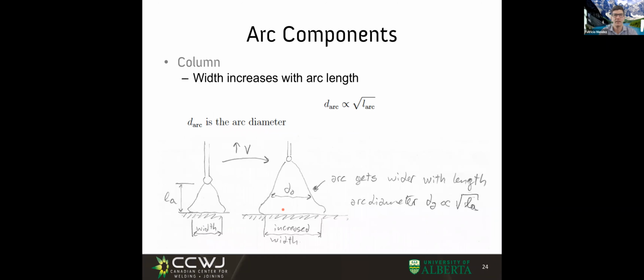Something else very interesting about the arc, both for MIG and TIG, is that the diameter of the arc is more or less proportional to the square root of the length of the arc. So the arc has this kind of bell shape, and it's not like a cone, it's like a bell. So if I increase my arc length, the diameter of the arc is going to be broader. But if I increase my arc length by 20%, the diameter is going to increase by more or less 10%.